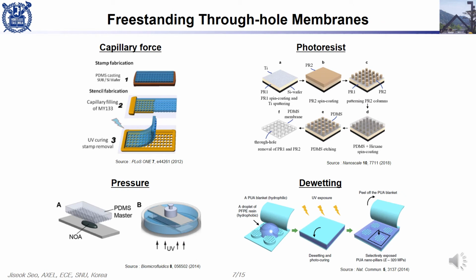To fabricate high-resolution pressure sensor arrays, I need a freestanding through-hole membranes. There are several methods for through-hole membranes, such as using capillary force, pressure, photoresist, and dewetting phenomenon. Among these methods, using dewetting phenomenon combining with spin coating process has no limitation of materials and no needs of pressure control or expensive photolithography process. So this method is applied to fabricate through-hole membranes.